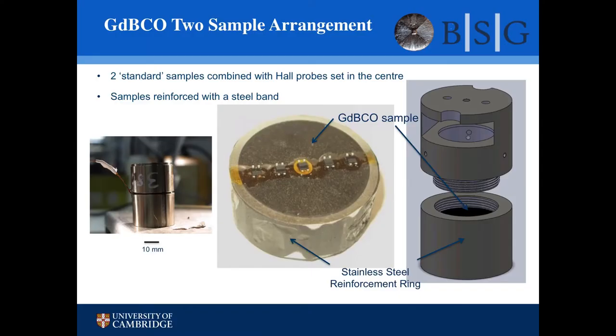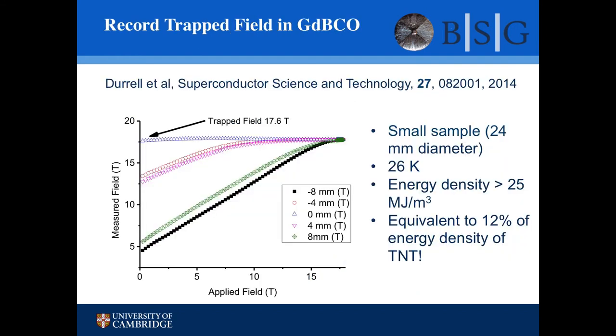And this was the arrangement. We took two samples, we put them in a steel container. We reinforced the thing with a steel band, and then you cool the whole thing slowly. You apply your magnetic field, then you remove the magnetic field. And here are the results. We've got a whole set of Hall probes across the sample to measure field. If you look at the one in the center, we apply the field, we remove the field, and measure how much field is left. And you can see here this is our record field, at the center of the sample when we have no applied field.